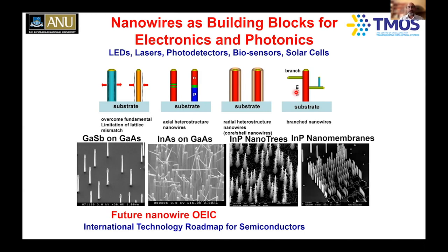So now you can see that in our own laboratory, we have demonstrated a wide variety of these nanowires. Gallium antimonide has been grown on top of gallium arsenide despite large lattice mismatch. We have shown excellent, atomically perfect gallium antimonide on top of gallium arsenide. For indium arsenide, we get branched nanowires, which can be used as cantilevers or scanning probes, for example. Nanotrees, in this case of indium phosphide, are very good for energy harvesting applications. And also going from nanowires to nanomembranes, we are exploring a wide variety of nanostructures for a wide variety of applications.